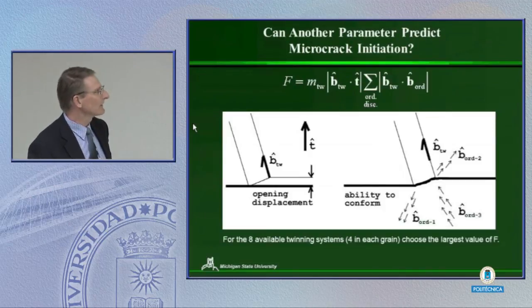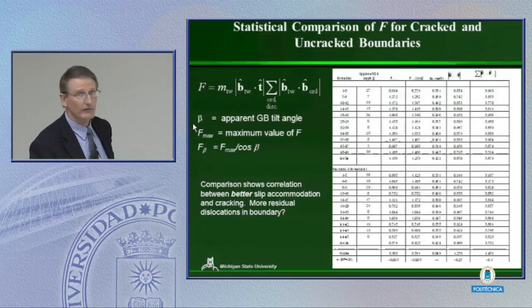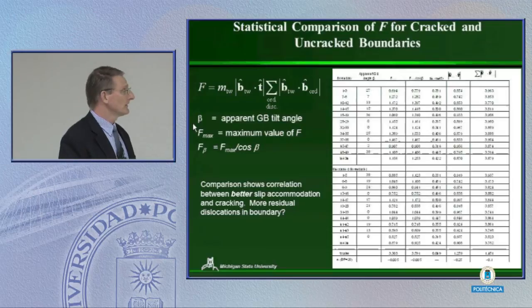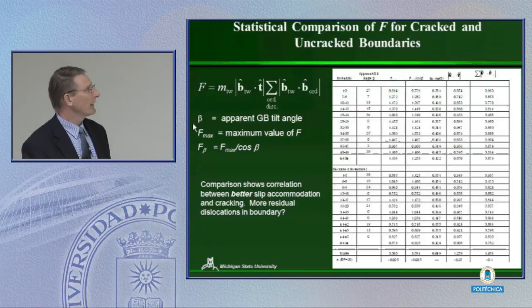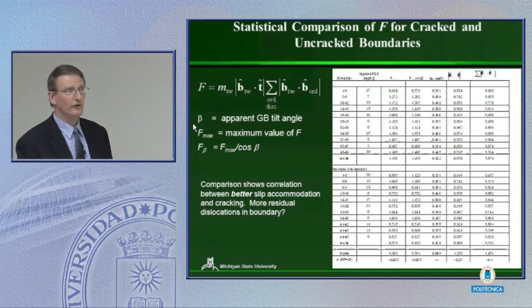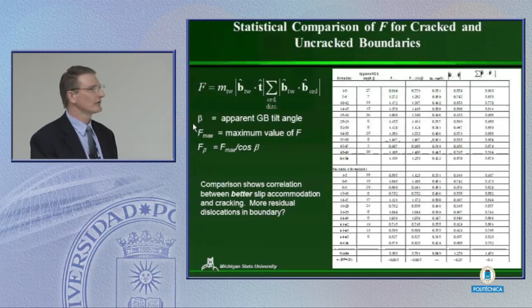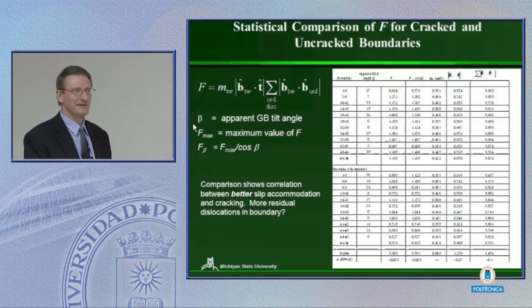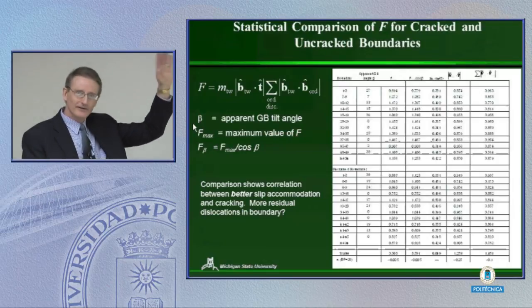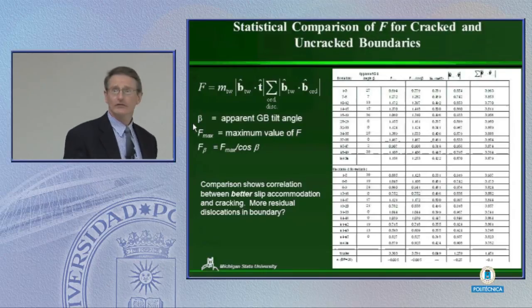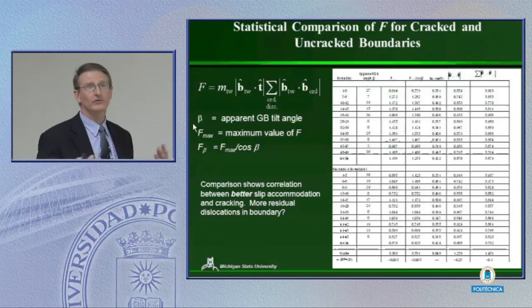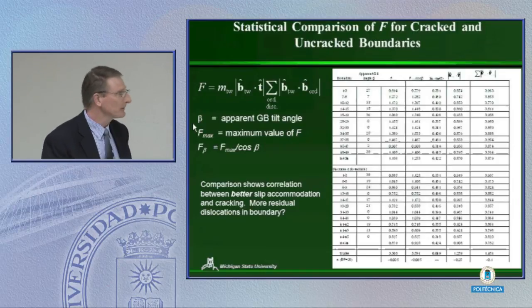So this kind of shows a model of this, where if we have cracking, we're going to have this situation. If we don't have cracking, we're going to have this situation, taking into account these various factors. So when we did that, we ended up looking at a couple of populations, a population of cracked boundaries and a population of uncracked boundaries. And I was going to kick out of this because I've done TEM for 30 years, and nobody ever does statistical analysis using TEM. And why is that? Because how many people have ever made a TEM foil? Okay. But this allows us to do enough observations for us to get some relatively statistically relevant types of data.